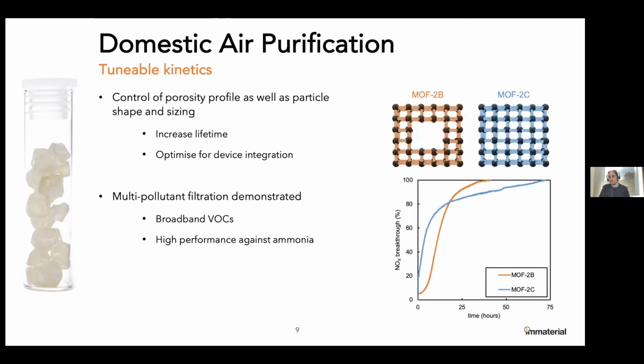Now, one of the other reasons why we're particularly keen to work with metal organic frameworks is because they have these regular structures which can be tuned in a very controlled manner. So MOF 2B, which was the results that I was showing on the previous page, still has a degree of mesoporosity, as indicated by this graphic here. We also worked on forming a fully densified MOF2C, so a variant of the same underlying structure, but just removing all of that mesoporosity.